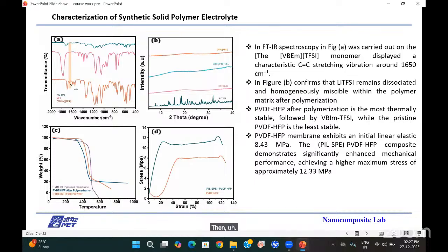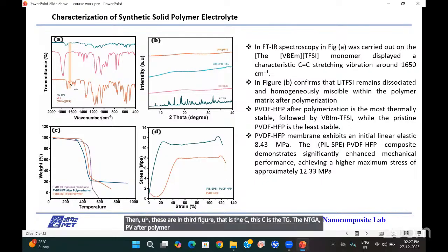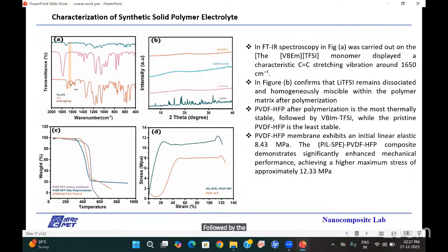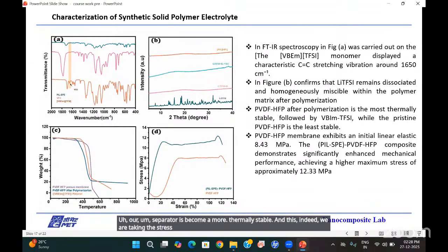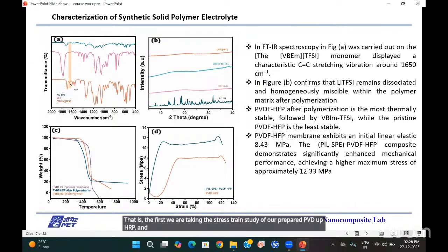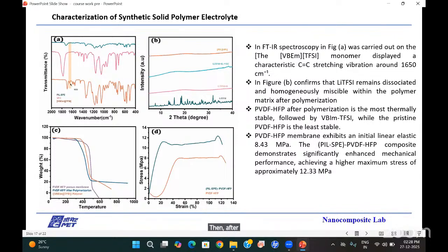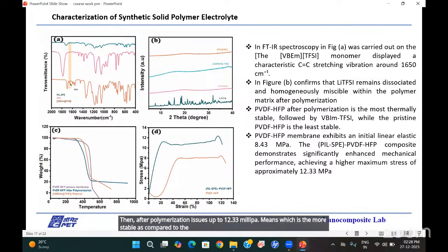Then in the third figure, that is C, this is the TGA. In TGA, PVDF-HFP after polymerization is the most thermally stable, followed by our ionic liquid polymer, and then pristine PVDF-HFP is the least stable. That is, after polymerization, our separator becomes more thermally stable. And in D, we are taking the stress-strain study. First we take the stress-strain study of our prepared PVDF-HFP, and then after polymerization. The prepared PVDF-HFP shows linear elastic stability up to 8.43 megapascal, and after polymerization it shows up to 12.33 megapascal, which is more stable as compared to the prepared PVDF-HFP porous membrane.